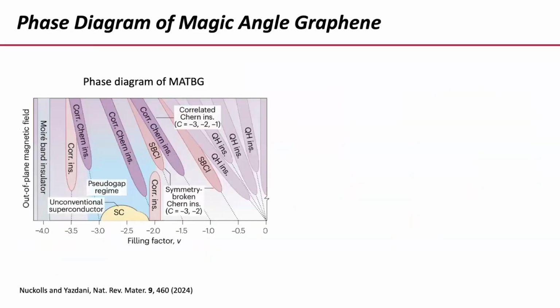This is a simplified phase diagram of magic angle bilayer graphene in this case, but all of them have very similar phase diagrams. This is in filling factor or doping. Okay, you can see a correlated insulator at 2 holes per moiré unit cell, then a superconducting dome, and a pseudogap. There are all kinds of quantum Hall insulators and Chern insulators of various types, which can appear.